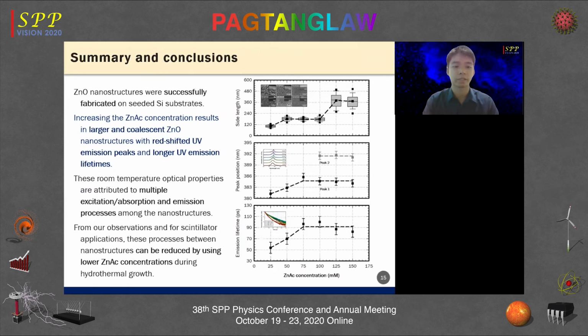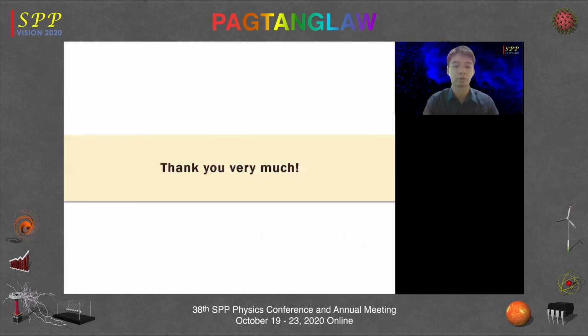concentrations. Increasing the zinc acetate concentration results in larger and coalescent zinc oxide nanostructures with redshifted UV emission peaks and longer emission lifetimes. These room temperature optical properties are attributed to multiple excitation or absorption and emission processes among the nanostructures. From our observations and for scintillator applications, these processes between the nanostructures can be reduced by using lower zinc acetate concentrations during hydrothermal growth.